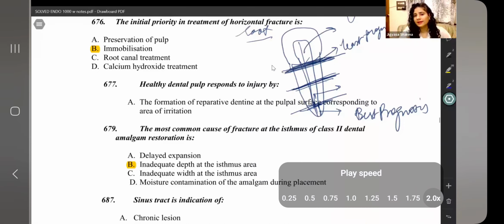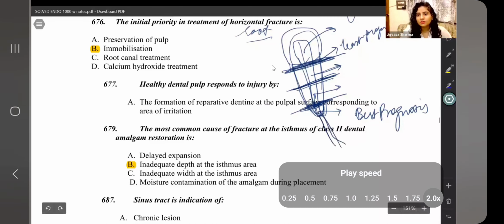So even if you get the signs of your coronal fragment going non-vital in your apical third fracture, by any chance, this is a coronal fragment, and below the fracture line would be your apical fragment. The apical fragment would always maintain its blood supply, very less chances that it will go non-vital. But if this got displaced, the chances are that the coronal fragment might lose its vitality. And when it does so, you'll find a radiolucency surrounding the fracture line, and you will find that the fracture fragments are separated by more than 1 mm.